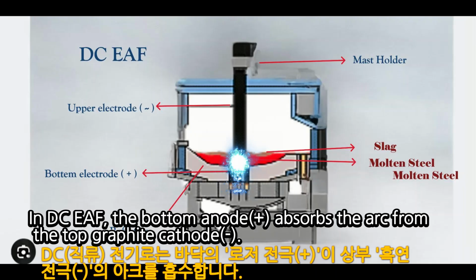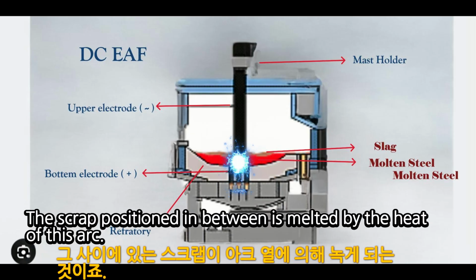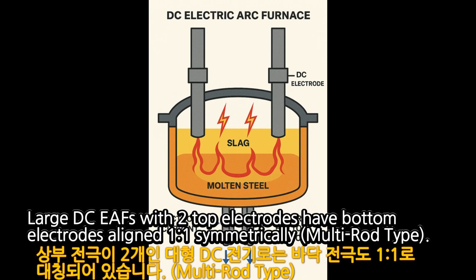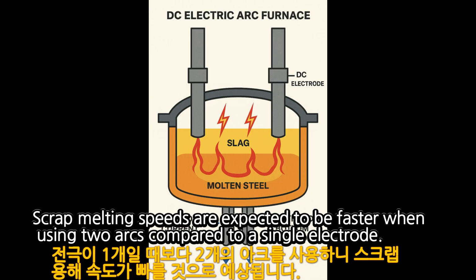In DC EAF, the bottom anode plus absorbs the arc from the top graphite cathode. The scrap positioned in between is melted by the heat of this arc. Large DCEFs with two top electrodes have bottom electrodes aligned 1:1 symmetrically, multi-rod type. Scrap melting speeds are expected to be faster when using two arcs compared to a single electrode.